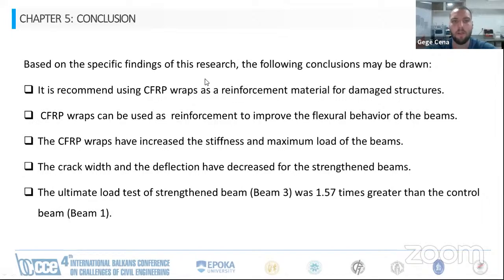Based on the specific findings of this research, the following conclusions may be drawn. It is recommended to use CFRP wraps as a reinforcement material for damaged structures. CFRP wraps can be used as a reinforcement to improve the flexural behavior of the beams. The CFRP wraps have increased the stiffness and maximum load of the beams. The crack width and the deflection have decreased for the strengthened beams, and the ultimate load of the strengthened beams was 1.57 times greater than the control beam, that is beam 1.